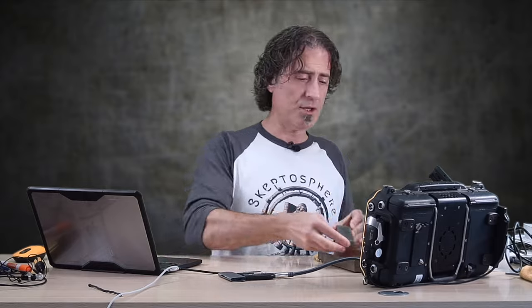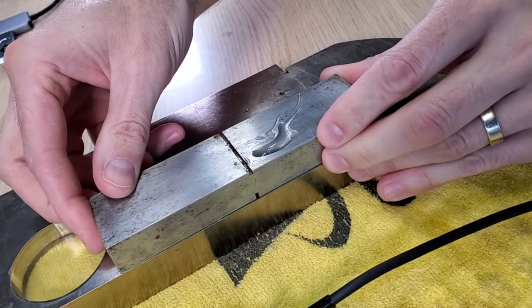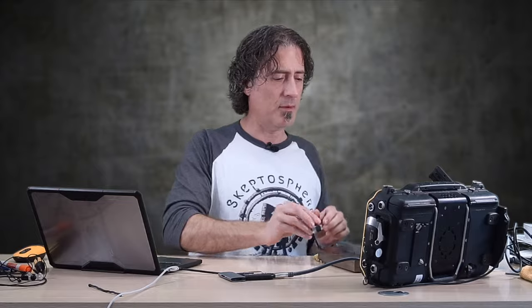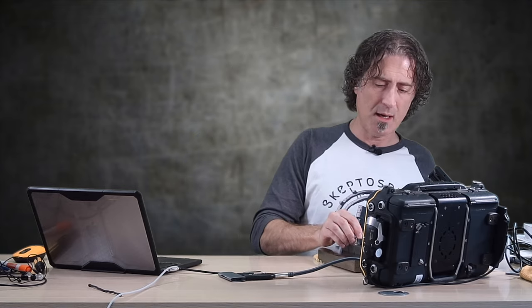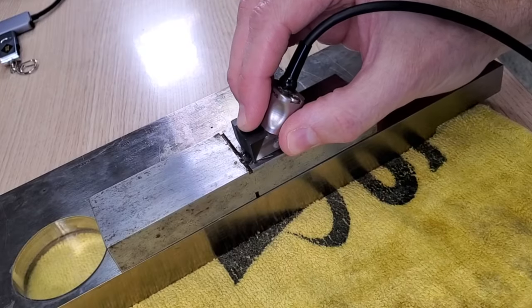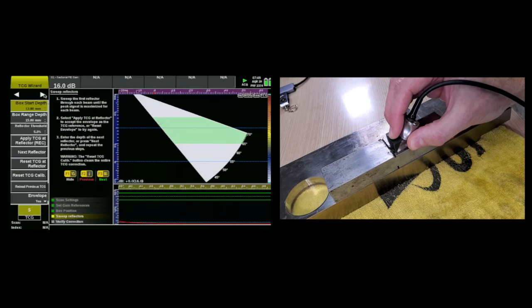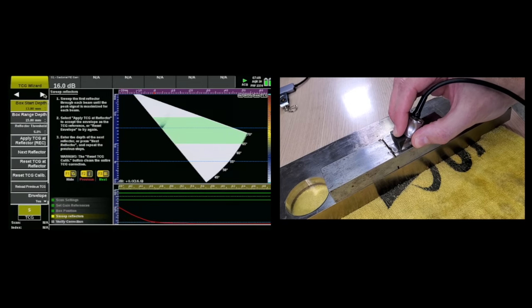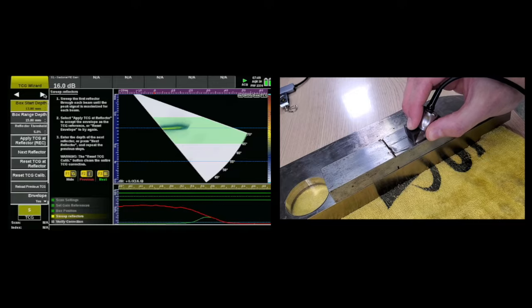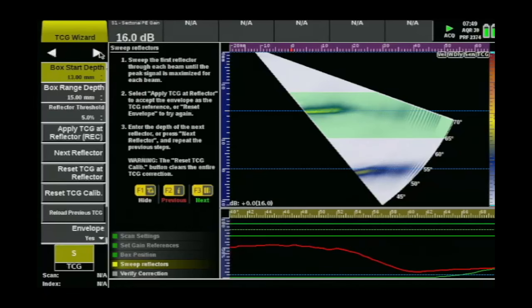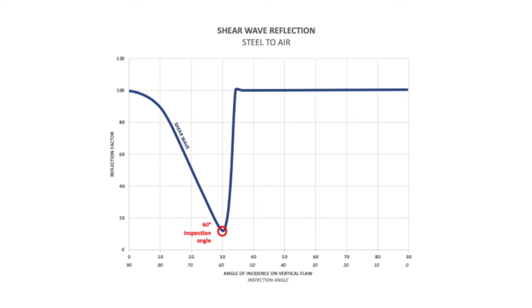Here I've got a block with a notch in it. We're going to use the 4mm notch on the bottom, which is about 20mm high. When I move the probe back and forth and go into the TCG calibration, pulling the notch all the way through the beams, you can see that right at around 60 degrees we just kind of lose everything. And that is this part of the graph right here — that is us losing 90% of the reflected shear wave energy.